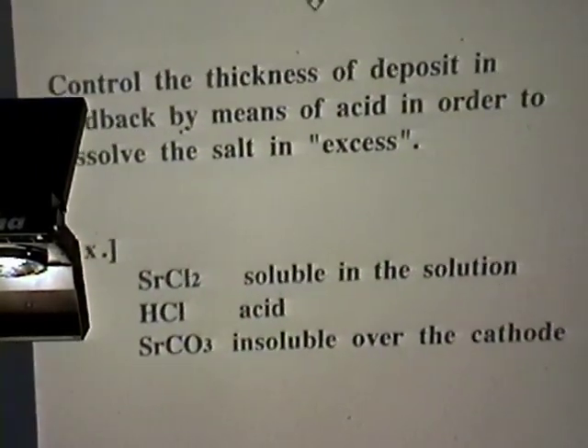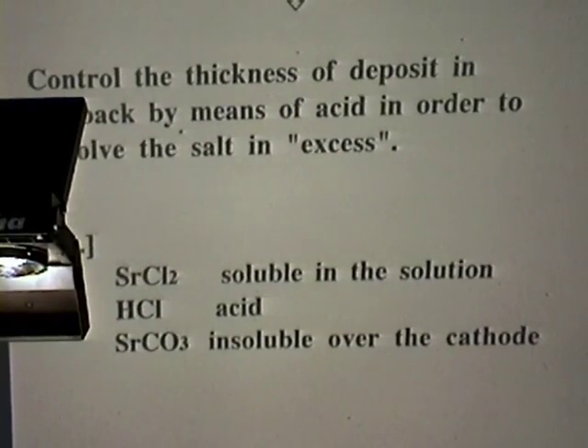So this procedure works with a slightly strange electrolyte solution, where we have a salt soluble in the electrolyte, but at the cathode the salt changes into another, insoluble one. We use the side effect of carbon dioxide, always dissolved in the light or heavy water, to make this trick. Moreover, if the thickness of the deposit is too large, the acidic solution dissolves the excess thickness.